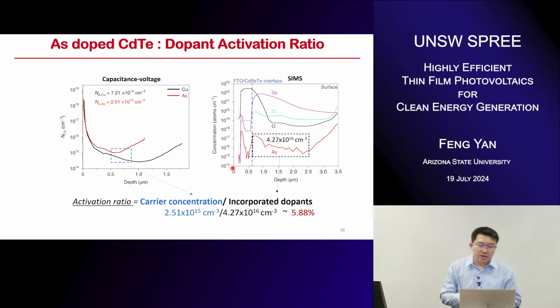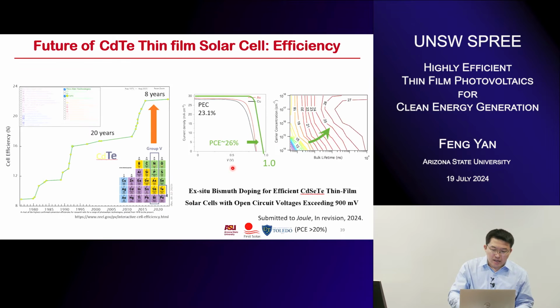Further characterization demonstrates a higher activation ratio. If we determine the carrier concentration using the capacitance voltage technique and then combine it with secondary ion mass spectrometry, we can demonstrate that the activation ratio is close to 6%, which is promising compared with 1% for copper or other ex situ doping. But we expect it can be further improved by tuning the processing or the device architecture, so it is ongoing work. And for the future of cadmium telluride, efficiency is still one of the major goals compared to